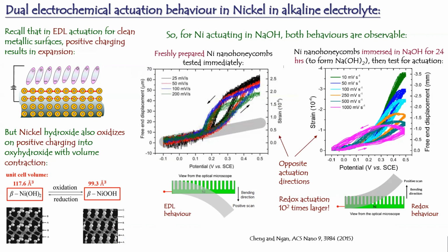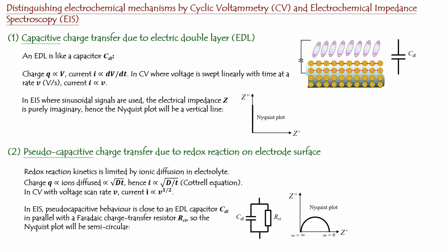And also, if you look at the scale, this is 10 to the power minus 6. This is 10 to the power minus 4. So this redox reaction, this redox actuation, is 100 times larger. So that's quite interesting. Same material, but you can have two mechanisms. There are further experiments that you can do to dig deeper into these two types of mechanisms. So if you run electrochemical tests like cyclic voltammetry, or what people call EIS, electrochemical impedance spectroscopy.